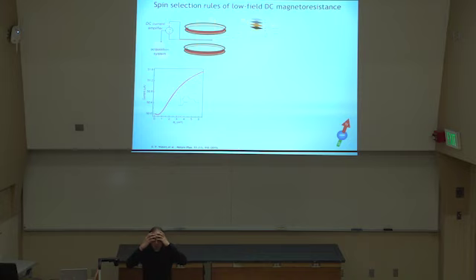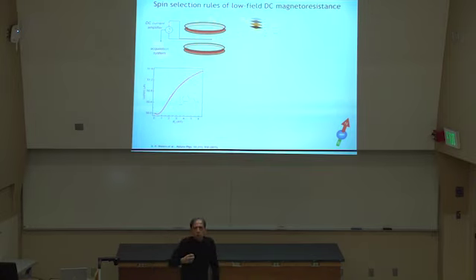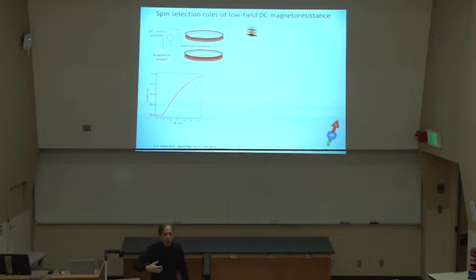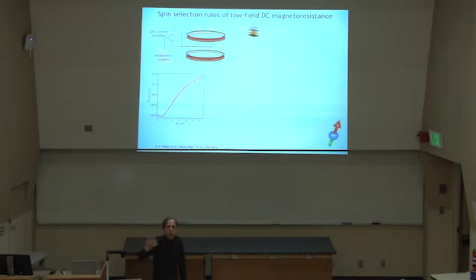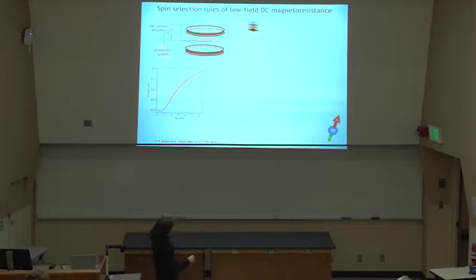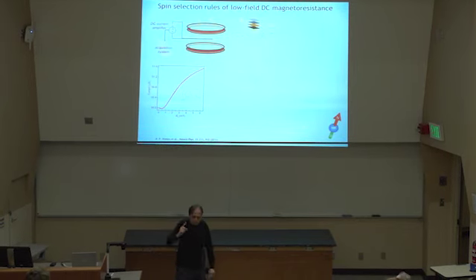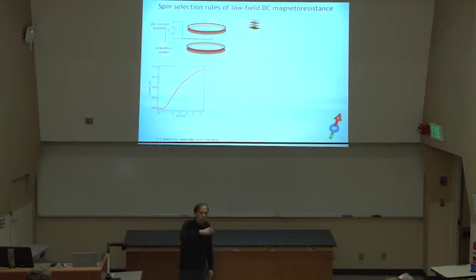Because naively you would say, well, first of all, can it be just some sort of Lorentz force effect on charge carriers? And you can rule that out very quickly. That doesn't work like the Hall effect. So it's really a spin effect. Fine. But if spin controls somehow electric current and charge transport and/or recombination, because we have a non-equilibrium here, then if spin controls current, you look at the polarization.